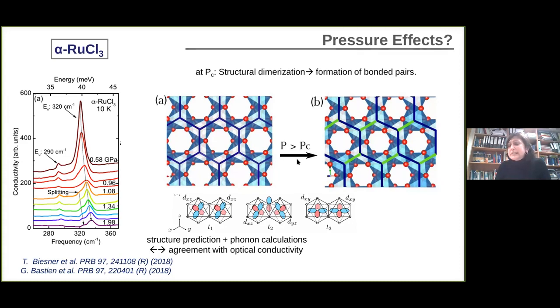And at the critical pressure, basically the system just distorts and forms singlets of nearby ruthenium atoms. So basically you go completely away from these Kitaev limits. And this is the conductivity experiments by Martin Dressel and collaborators, where they find that at about 0.9 gigapascals, the corresponding phonon splits, and there is then this phase transition.